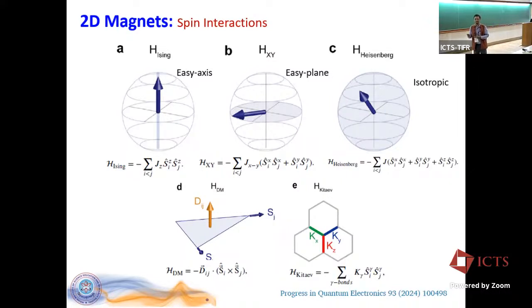If you look at the Mermin-Wagner theorem, it basically says that unless you have anisotropy, you cannot have long-range ordering in systems which are less than three-dimensional. So in 2D systems, the kind of spin interactions we can think of: this is basically an isotropic system where the spin can have x, y, and z components. That can be modeled through the Heisenberg Hamiltonian.